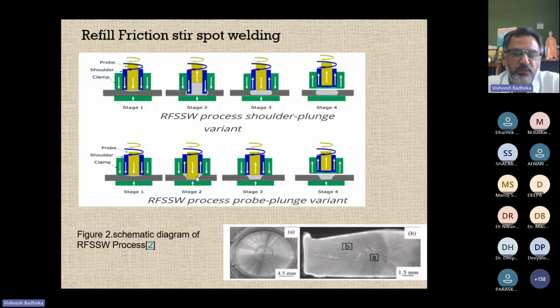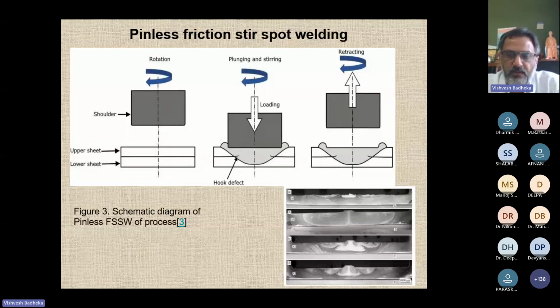You see that the pin is going down and the shoulder is going up, completely opposite to stage 2 here, right? And then in stage 3, it is opposite to this one. The pin is going up, shoulders are going down, right? You can see the deformation at the interface, and you can see here also, and finally the joint. So this is called refill friction stir spot welding. So here also, for understanding, I have a small clip for all of you. Yeah, let me show if I can.